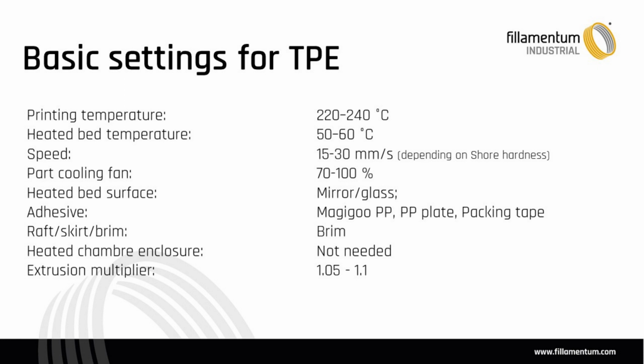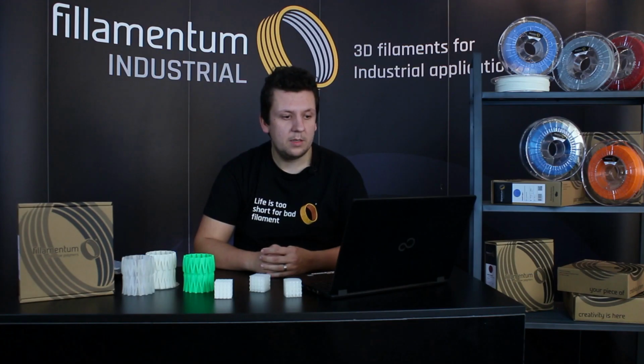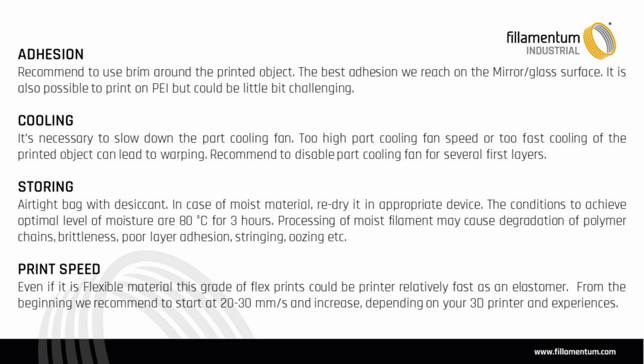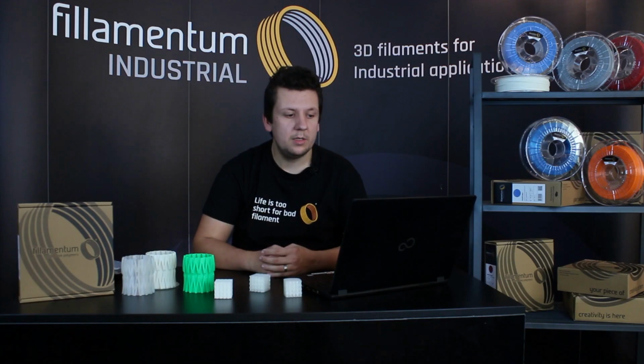So now let's take a look at the TPE and what is the difference in print settings against the TPU. If you look at the presentation, you can clearly see that the main parameters are almost the same or the same. The main difference is definitely the adhesion. So therefore we recommend to use a large brim, and as our TPE is based on polypropylene, for the adhesive we recommend Magigoo for polypropylene plates or packing tape made of polypropylene, which ensures good adhesion for achieving a good print.